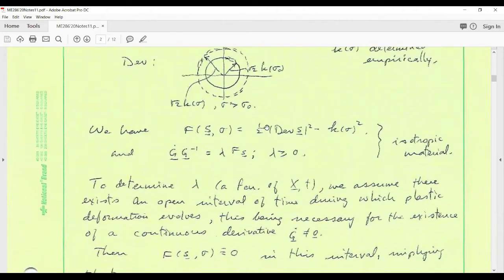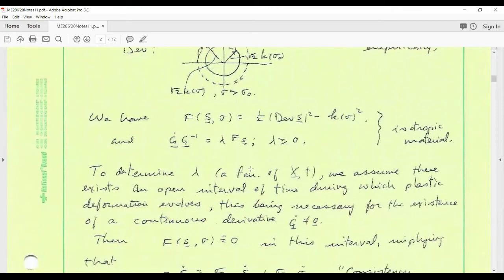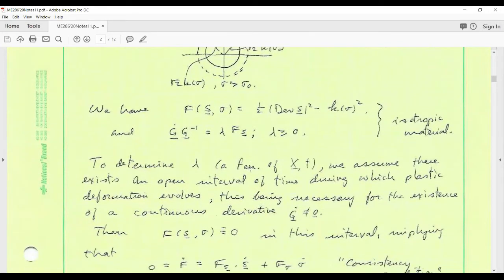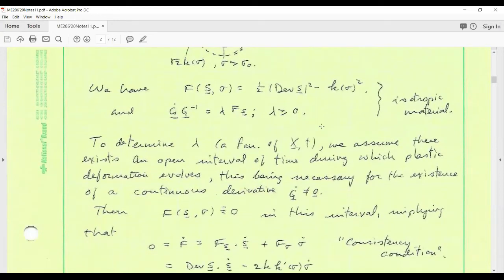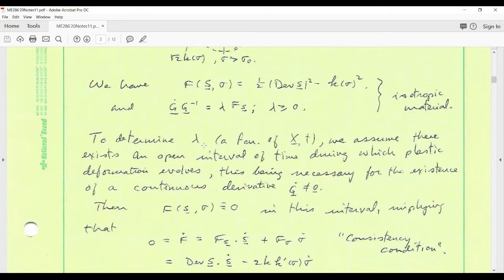Here is the flow rule for isotropic materials — we argued we could suppress the plastic spin and that's what we've done here. We cannot do that for crystalline materials. Lambda is some function of position and time, to be determined in the course of solving a problem, and it must be non-negative to ensure a physically admissible process. Interestingly, with hardening taken into account, we can actually determine lambda. Before, we really couldn't say anything specific about lambda — we had to determine it directly as an additional variable. Here we can actually say more about lambda a priori.